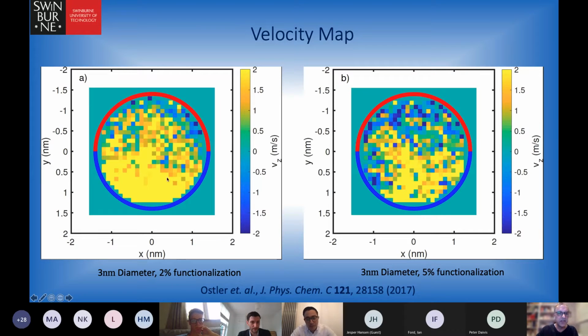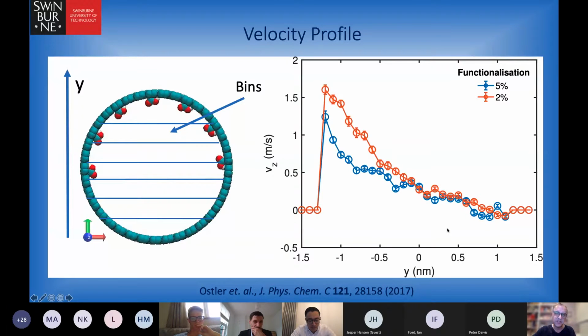So here we've got a 2% functionalization on the top half of the carbon nanotube over here. The flow is reduced in the top half, and it's more intense in the bottom half, as you can see with this velocity map. As you increase the functionalization, perhaps counterintuitively, you might think, well, surely you increase the velocity flow, but in fact you decrease it. The reason is that as you increase the functionalization, you increase the number of carboxyl groups protruding into the nanotube itself, and they tend to block the flow of water molecules. So there is a bit of a sweet spot in terms of the degree of functionalization.